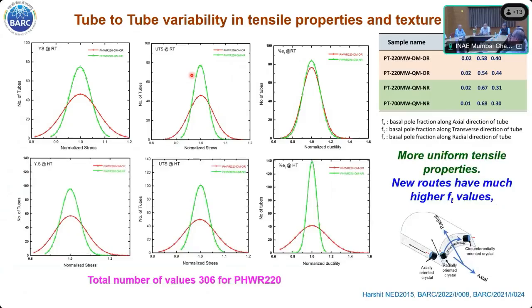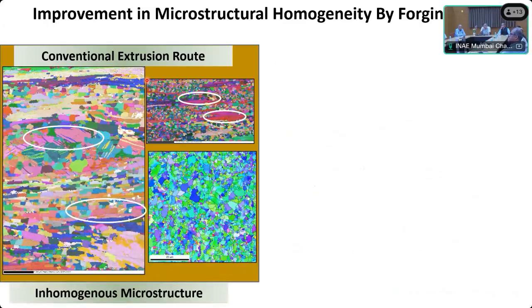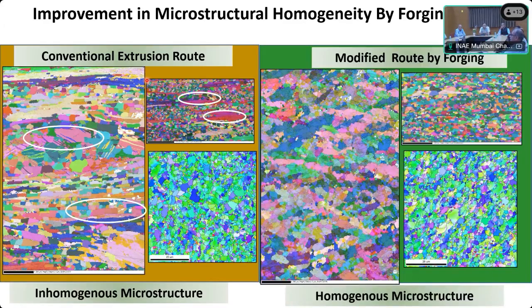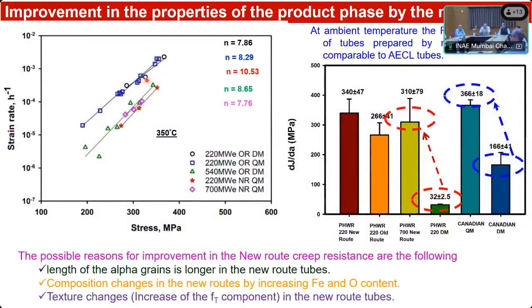The first change was in the mechanical properties: all the UTS values, their deviation came down. It became much narrower compared to what we were having, where the trailing side and leading side had a lot of property variation. Tubes were having a lot of problems, and many of these problems were solved. Microstructurally, this is the old route, where you can see the patches marked by the elliptical circle. On one side there is one crystal structure, and on the upper side you can see another grain size. So there is a variation in property because of this non-uniform microstructure. When you have done the forging, these parts have gone and the structure has become very uniform.